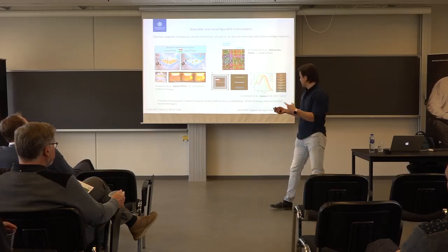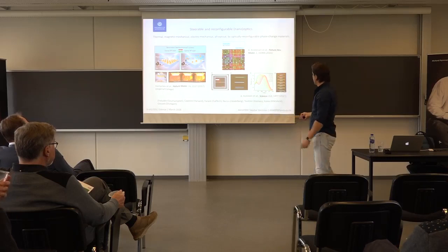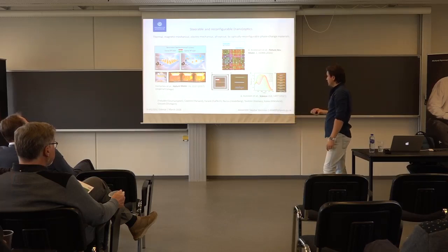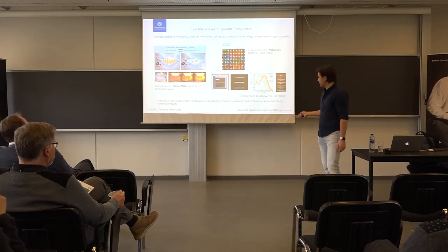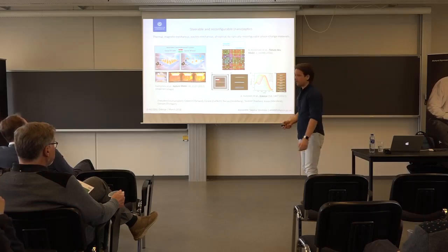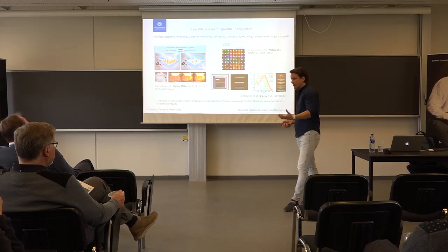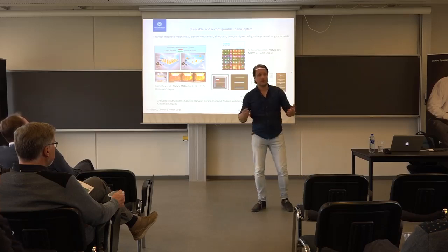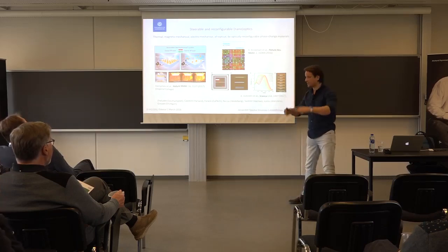Well, the spacing there is like half a micron to the mirror, and then it moves, let's say, 100 nanometers by applying different voltages, but that amazingly changes the color of that wire. So you already have electrically tunable color of the scatterer of the visible light. It is not extremely fast, so you can probably do it best in megahertz, because then it enters into the resonance of the entire frame.